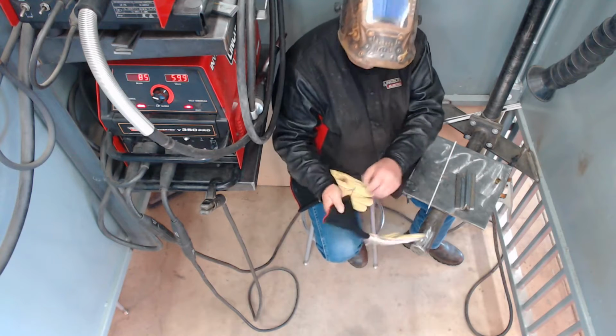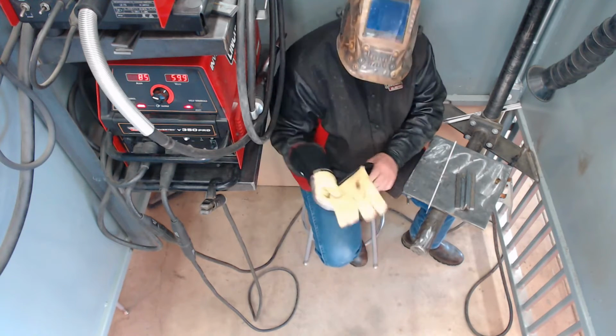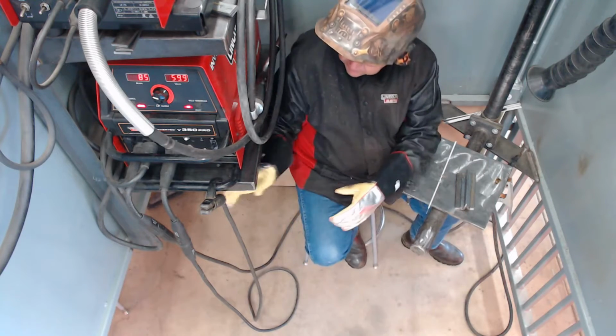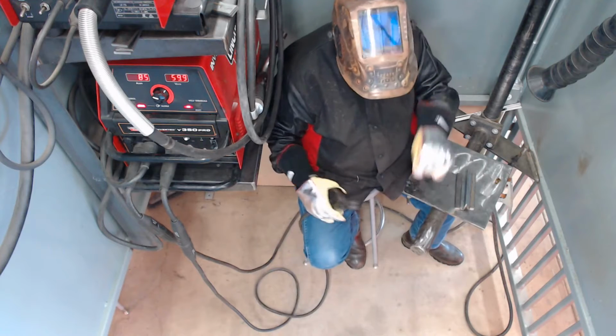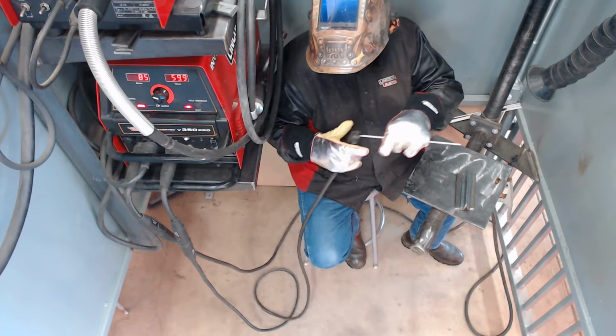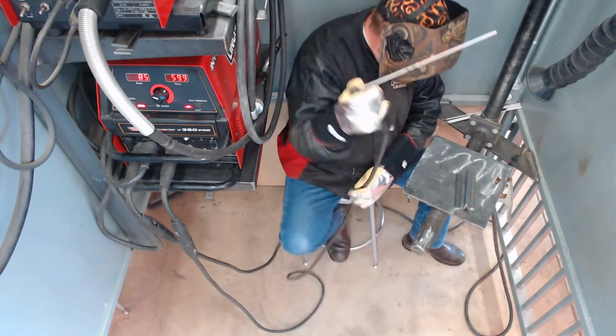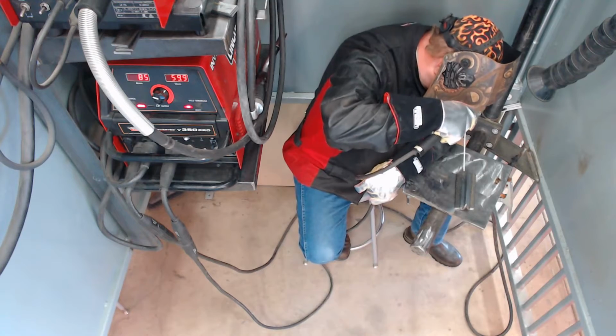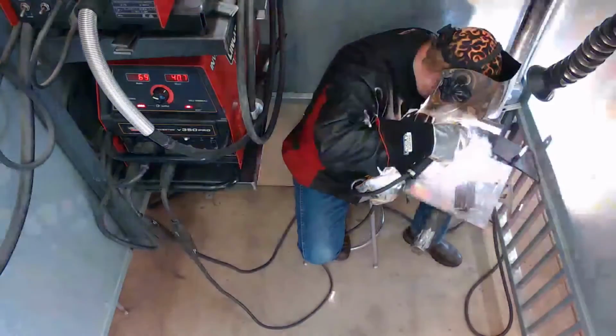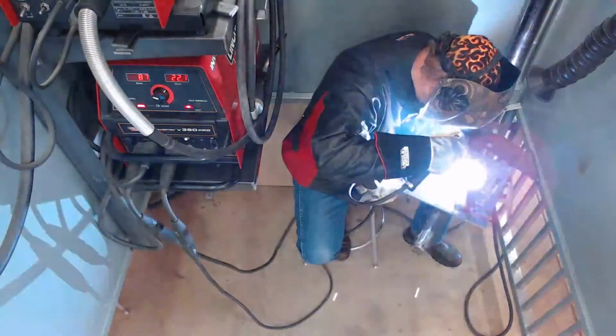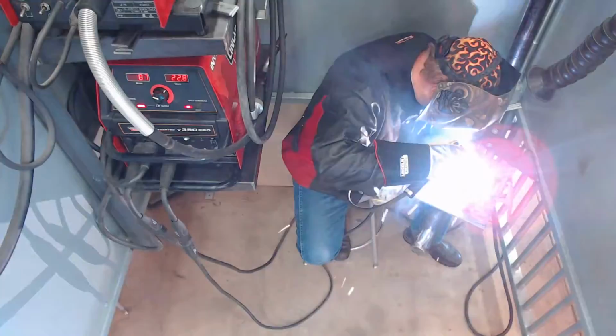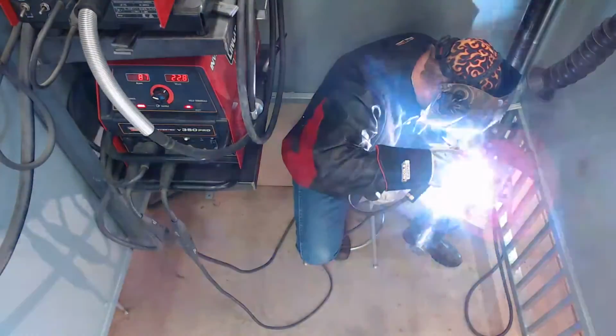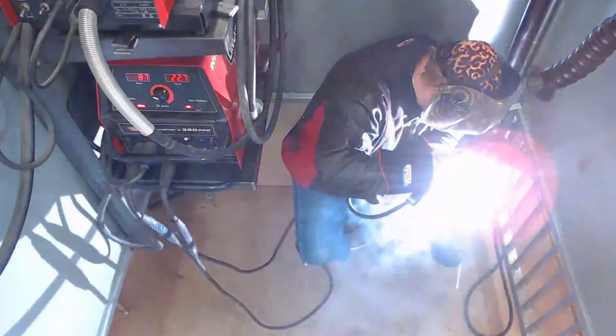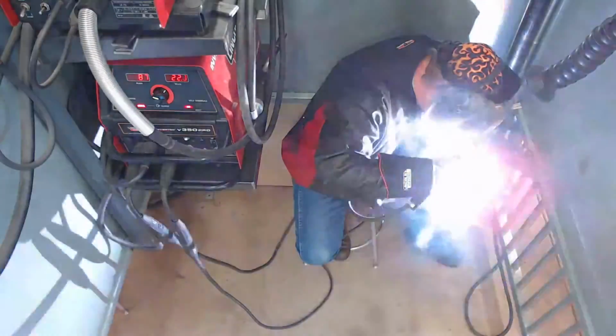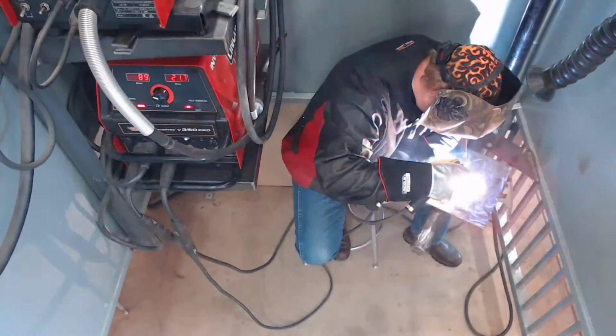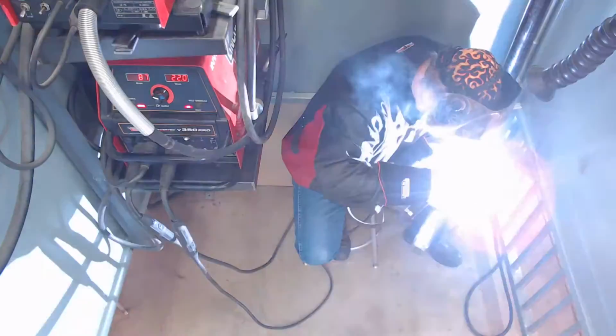First pass on a two-pass bead. Again, with E7018, our setting is at 85 amps. We're using a 3/32 electrode. And here we go. Okay. You can see my electrode's almost perpendicular to the weldment. I'm striking my arc, and just dragging my electrode in a back motion. The cool thing about 7018 is I can feel the flux pretty much as it melts off of the electrode itself.